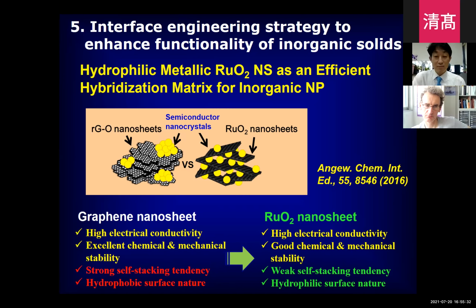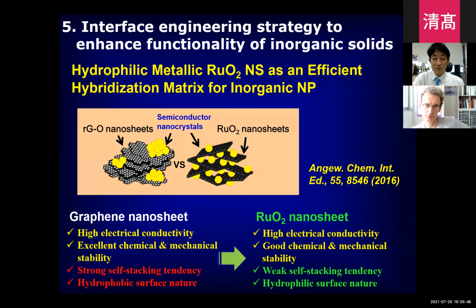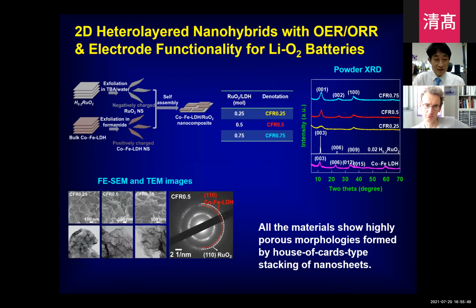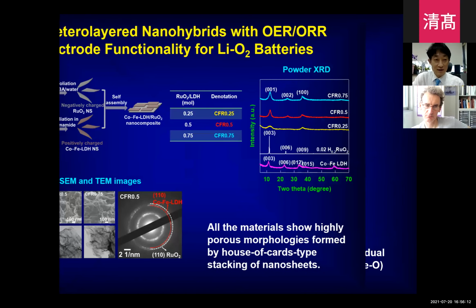We published a lot of papers about the merit of hybridization with ruthenium oxide to enhance the photocatalytic activity and electrocatalytic activity of inorganic nanostructures. That's one example. We hybridized ruthenium oxide nanosheet with the LDH. We synthesized an intimately coupled hybrid material composed of the LDH and RuO2 nanosheet. We confirmed the formation of the homogeneous hybrid material from electron diffraction analysis.